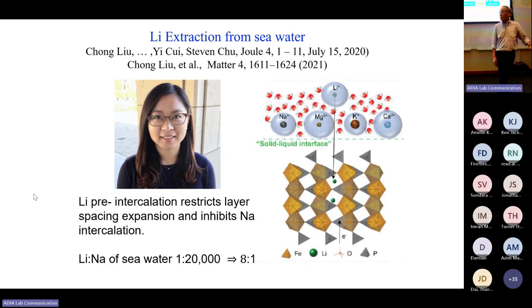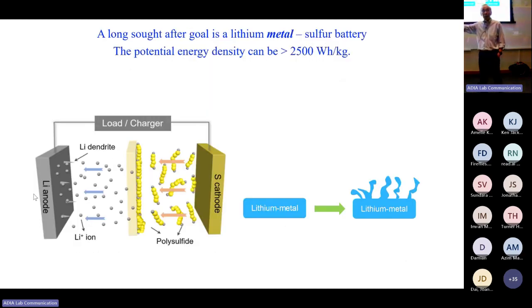Another thing is batteries, conventional batteries. The highest energy density batteries are those where you have a pure metal anode. And if it's a lithium ion battery, it would be a lithium metal anode, but it doesn't have to be lithium. One is not wedded to lithium. And in fact, with utility scale batteries, you can't use lithium. But the trouble with a metal battery, any kind of metal, doesn't have to be lithium, is that when you charge very quickly, there could be surface imperfections.